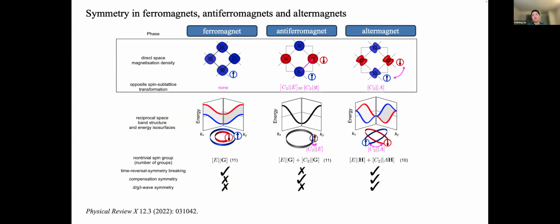For altermagnet, since the sublattices have rotation symmetry, the spin-up electron and the spin-down electron's orbitals have an angle with each other, which will break the time reversal symmetry. And this will generate the alternating spin splitting. The altermagnet case is critical for our motivation, since it may produce novel proximity-induced effects when it interfaces with the superconductor.